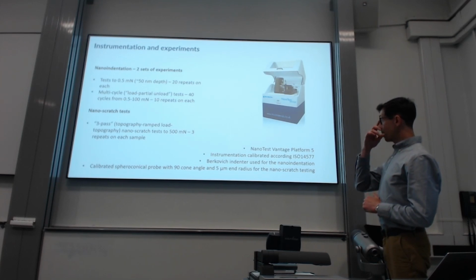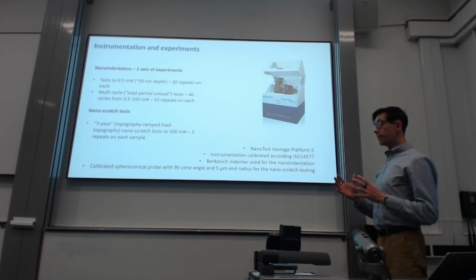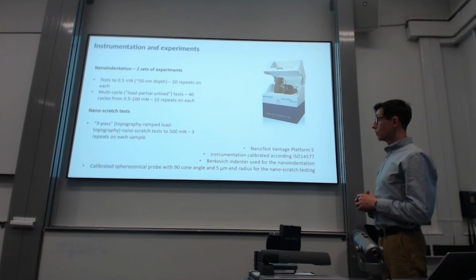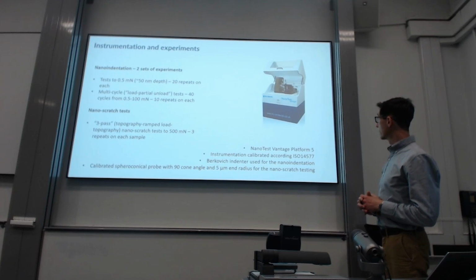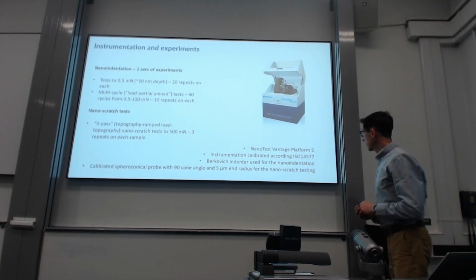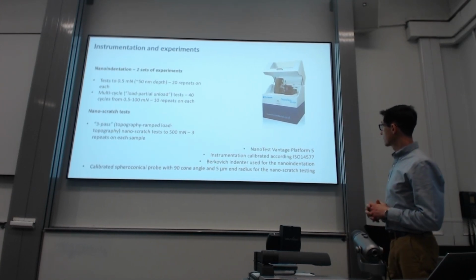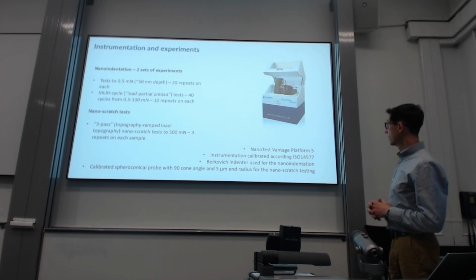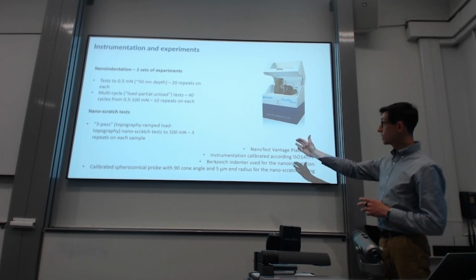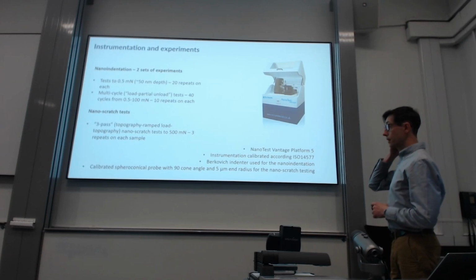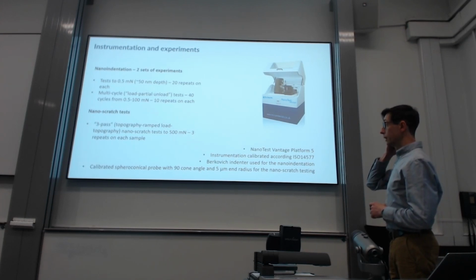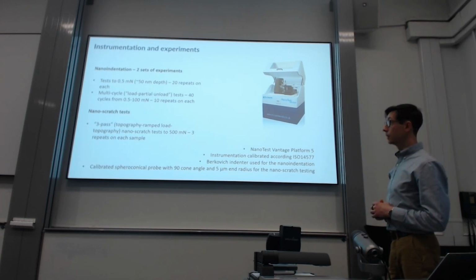And then we ran nano scratch tests in the 3-pass mode, well known to many of you, but I'll go through some fundamentals of that type of experiment. So, of course, the Platform 5, the NanoTest Vantage system, was used here. We used a Berkovich indenter for the nano indentation experiments, and a spheroconical probe for the nano scratch testing.